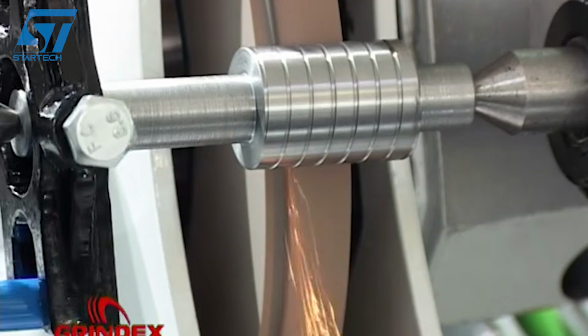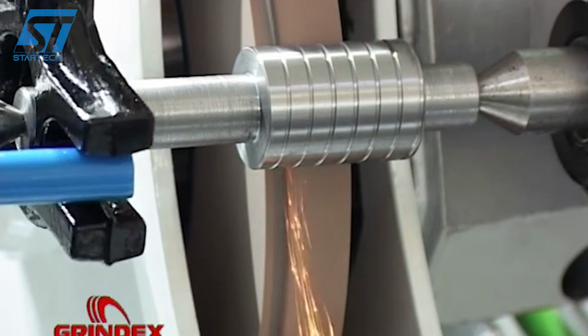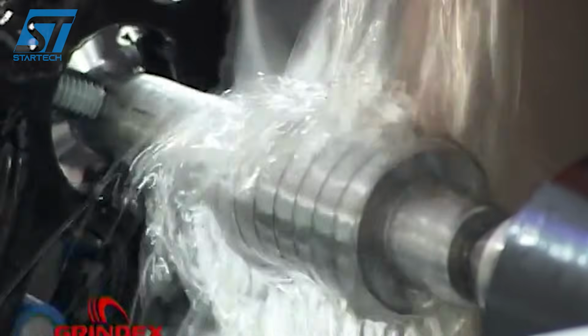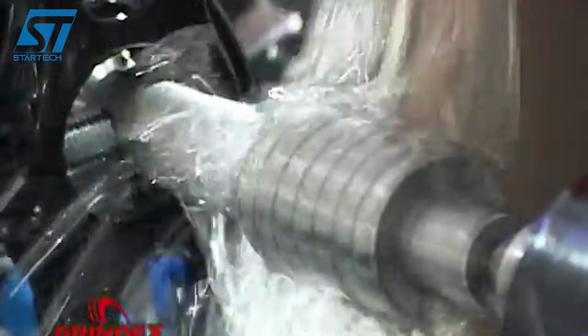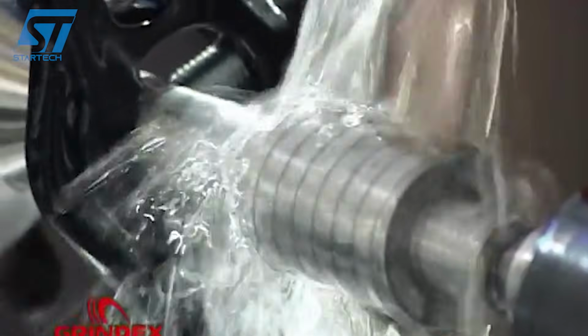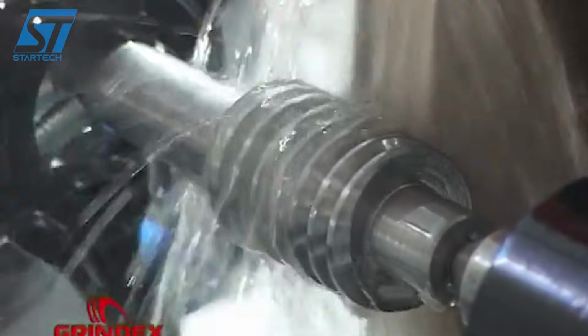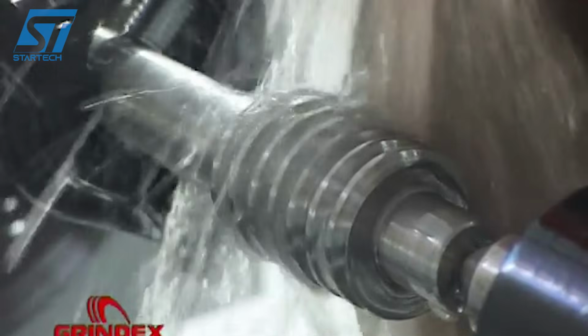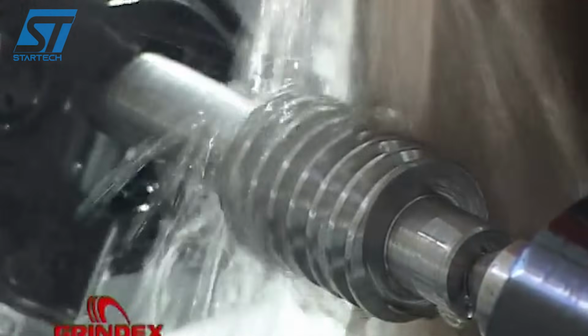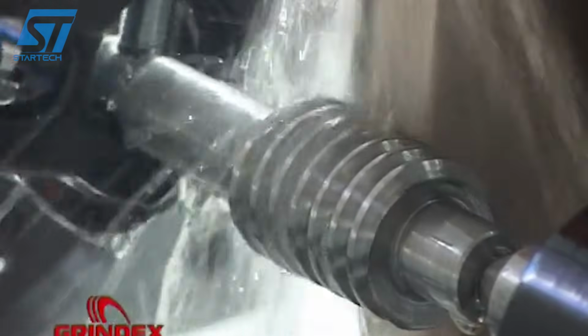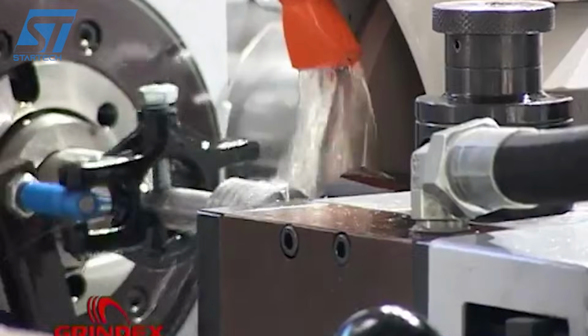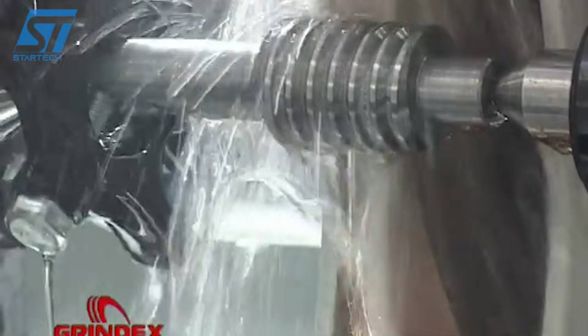What makes the CNC control system so valuable here is its ability to continuously adjust the infeed, traverse rate, and wheel compensation in real time as the grinding wheel wears down. Thread grinding wheels are made of aluminum oxide or CBN, cubic boron nitride, and they're dressed to the exact thread profile before each cycle. As the wheel removes material, the CNC compensates automatically, keeping the thread form perfect throughout the entire grinding pass. The process itself is a form of generating grinding.